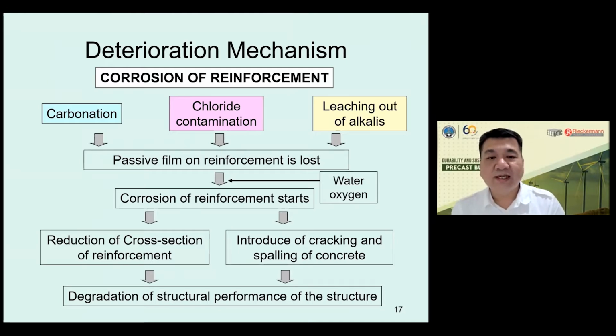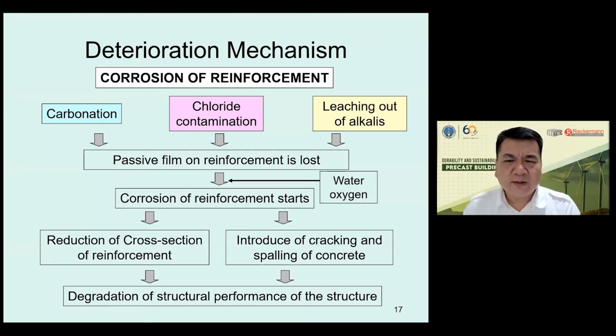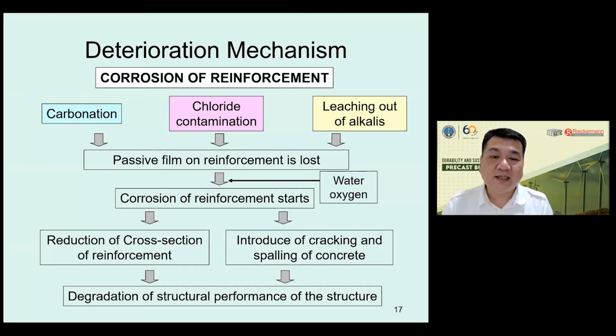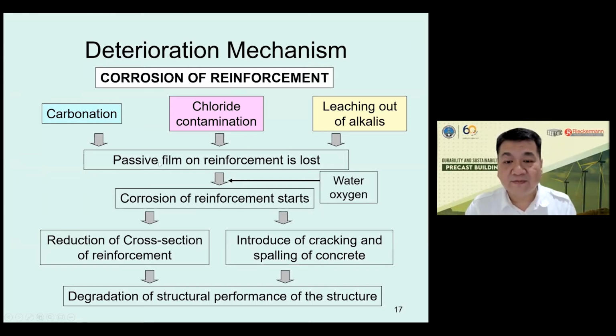So for new concrete with reinforcement, normally the reinforcement is protected by the concrete. The passive film is like a layer on the reinforcement surface. Due to the high alkalinity of the concrete, we have the passive film. The passive film normally protects the reinforcement from corrosion.